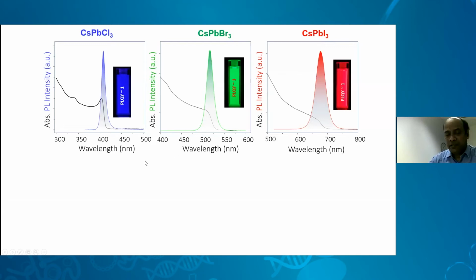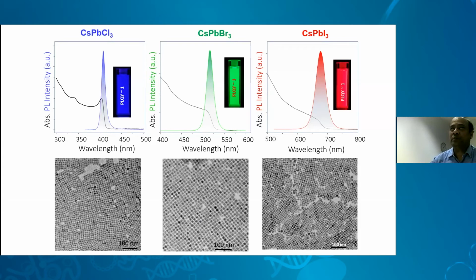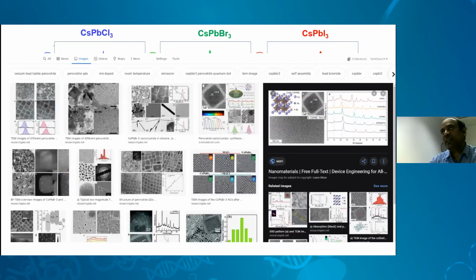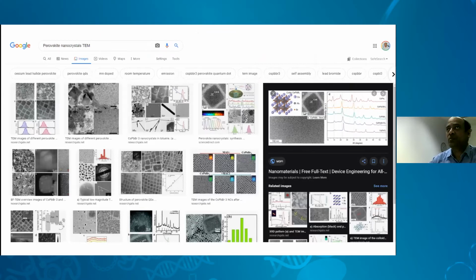So now what is unique here, other than the colors? If you look under the microscope, you see these are all cubes. Irrespective of their colors or composition, they are exclusively formed as cubes or platelets, as I was showing before. To understand that, I also put the words perovskite nanocrystals and TEM in Google. You could see most of the cases are cubes. Basically, it's a fundamentally challenging problem. Why are these cubes? Why can't several other facets be created? Facets are important for catalysis, facets are important for assembly, and facets are important for designing different patterns or growth, secondary growth, or getting heterostructures of these materials.